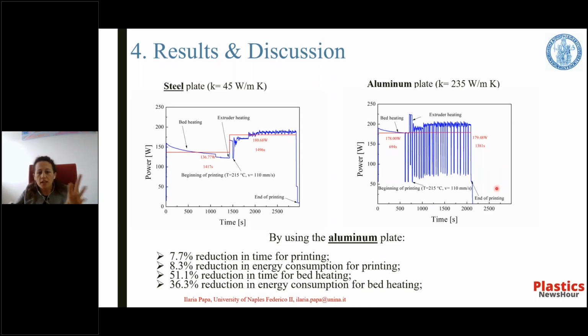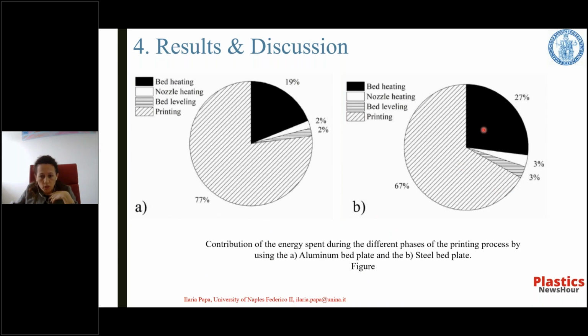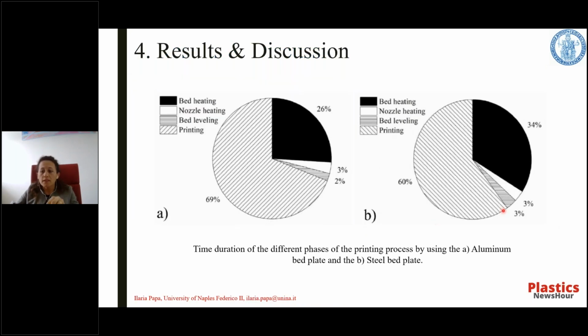So in this slide, in the pie charts, we show a decrease in the bed heating contribution and an increase up to 70% of the energy spent for the printing phase, which is the only value added phase, because just in this phase the workpiece is built. The same behavior is reported in the phase duration pie charts. As you can see, the rapid heating of the aluminum bed plate allows the increase of the time percentage spent to print the component.